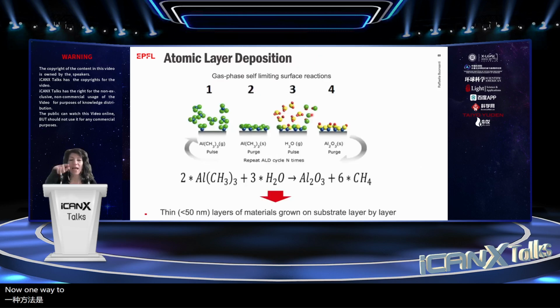Now, one way to create very thin layers of oxide is atomic layer deposition. This is a technique which is normally performed on thin films. For example, if the goal is to deposit aluminum oxide, first we pulse trimethyl aluminum in the gas chamber of this atomic layer deposition tool. Then this TMA reacts with the surface. Then we purge to eliminate the excess TMA, and then we pulse water that reacts with the TMA, and eventually the first aluminum oxide layer is formed, and then the cycle can be repeated.